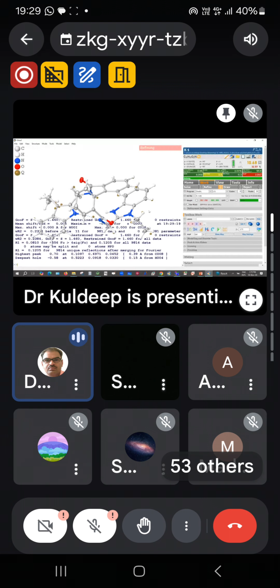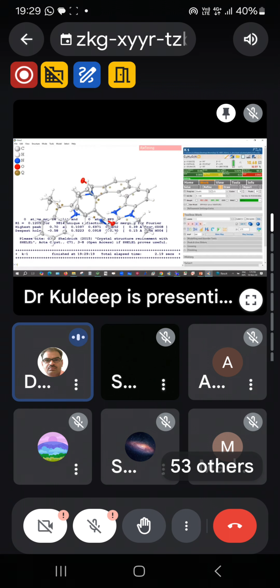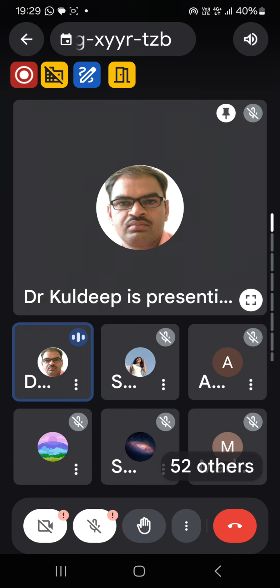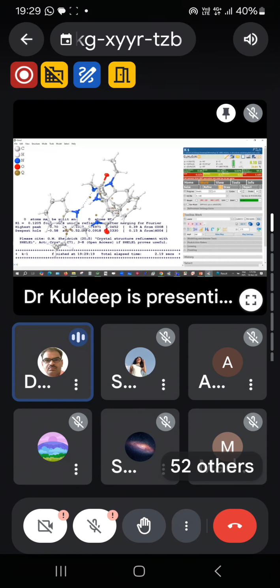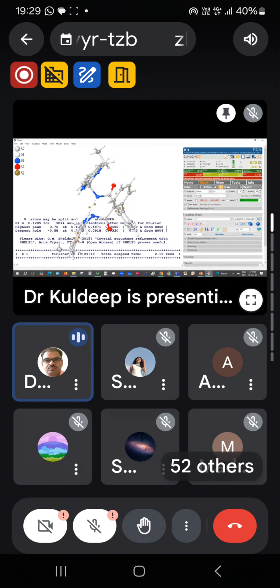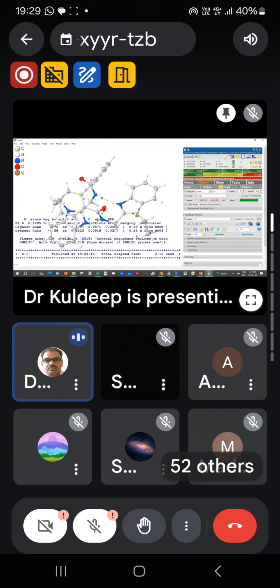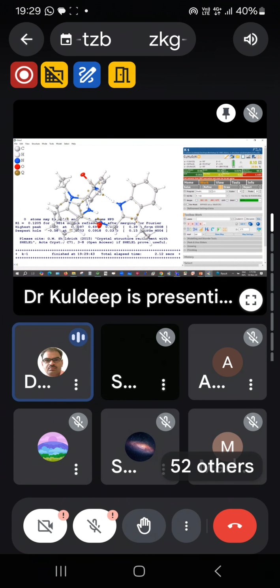Okay, now the R factor further drops to some 8.10%. Now I will refine one more cycle so that this shift gets stabilized, becomes almost 0. But I can see my goodness of fit is not yet around 1. This is still some off value. Maybe I am missing something in my model. Otherwise, it should be equal to around 1. So then I press Control M.